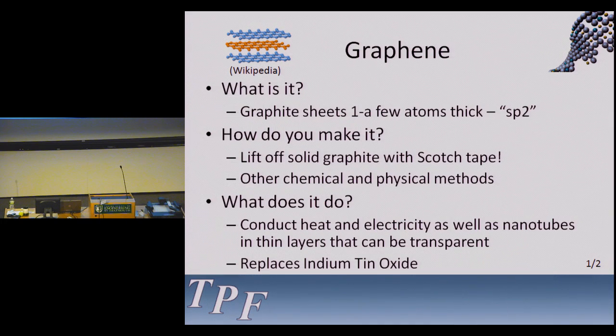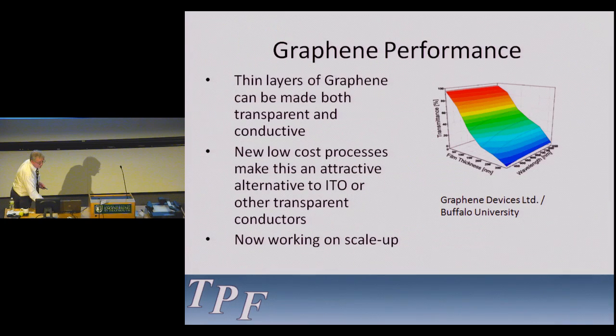What you really want to do is separate these layers by intercalating chemically, then separate the layers, then reduce them. And then you can put them down onto surfaces by electrophoresis or other techniques. And it produces a really interesting conductive material. And it can replace indium tin oxide, which is the conductive material that's used on touch screens. It's used in every flat screen TV, every computer here. And there's an issue of supply of indium going forward.